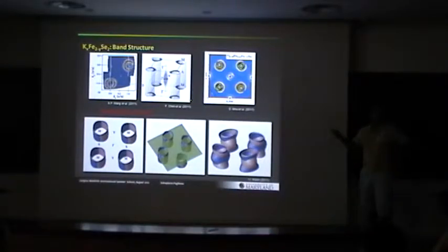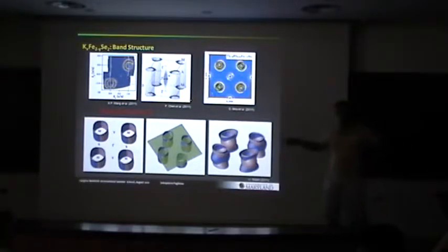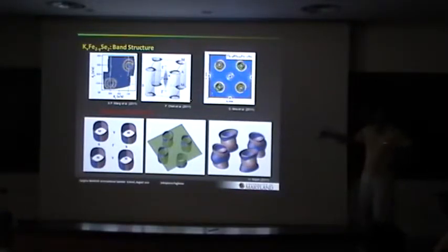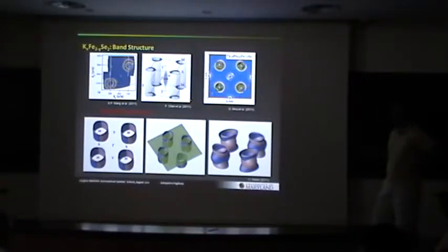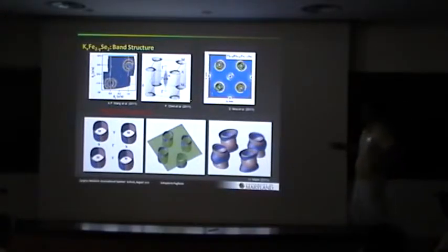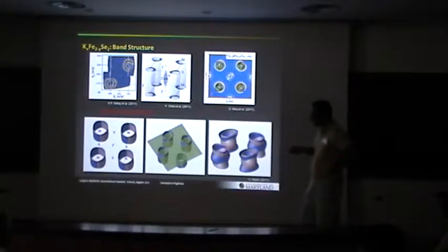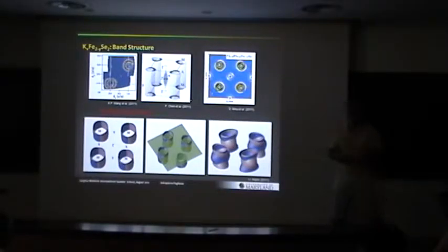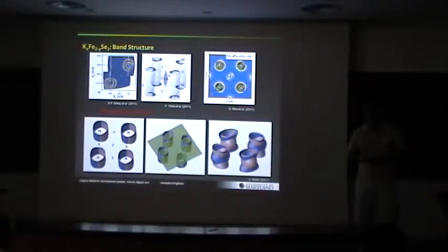So this is unique because here we have a 30 Kelvin superconductor. We have no hole pocket, and we have large moment antiferromagnetism. So it's in a sense thrown a wrench into the understanding of the iron arsenides to some degree, at least at the level where people think that there's some nesting vector between the hole and electron pockets that plays some important role in the pairing mechanism.